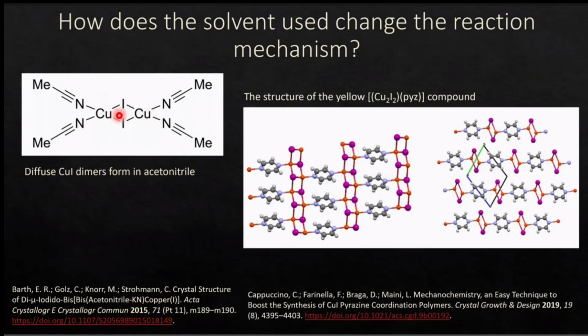Now, this mobile dimer phase, as we call it, seems to make it much easier to form this ladder motif in the yellow compound whenever you have these mobile dimers in place. And so they can snap together, like Legos basically, and form these ladder structures, which can be combined through pyrazine. And so this is one pathway where the solution synthesis in acetonitrile can lead to this yellow compound while completely ignoring the other pathway because there's so much acetonitrile around.